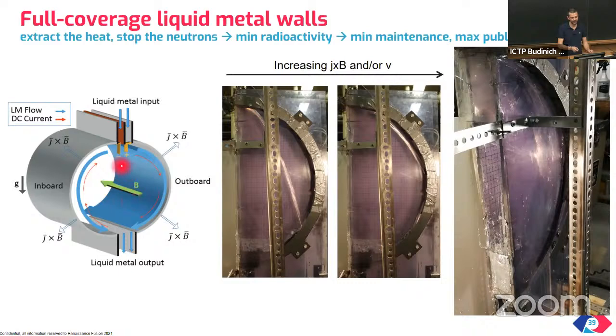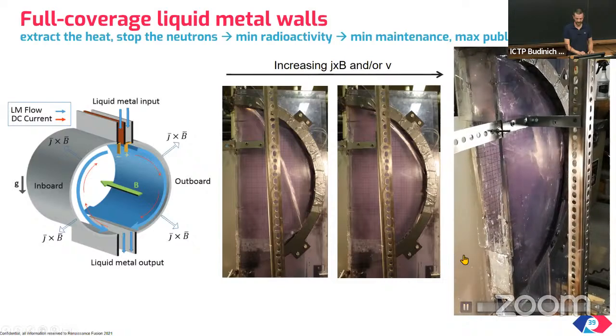Remember, we are in the presence of a strong B, so just applying a current in the liquid metal by means of electrodes in proper direction gives you forces pointing upwards. At the end of the day, parallel currents attract each other. You have these parallel currents in the HTS coils on the outside. You have parallel currents in the liquid metal, which is a deformable medium, on the inside. The currents on the inside tend to move towards the current on the outside, and so the liquid metal tends to stick. It does so better and better if you increase the electromagnetic force and or the velocity, and thus the centrifugal forces.